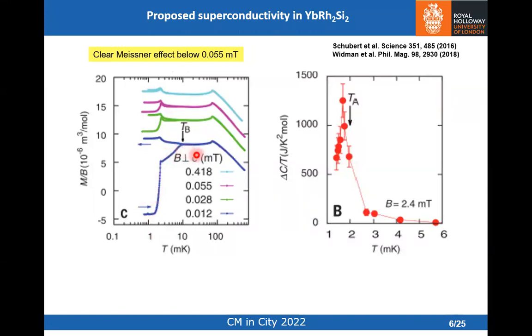And there's this interesting precursor feature, which is going to be relevant later on, at a temperature T sub B. And this notation for characteristic temperatures I'm going to be using throughout the talk to label features that we also see. The other very interesting observation by these guys was they measured the heat capacity at an in-plane field of 2.4 millitesla. So they had to subtract what they believed to be the quadrupolar heat capacity from the data. This is what's left after you've done that, and what you see is this anomalous feature in the heat capacity.